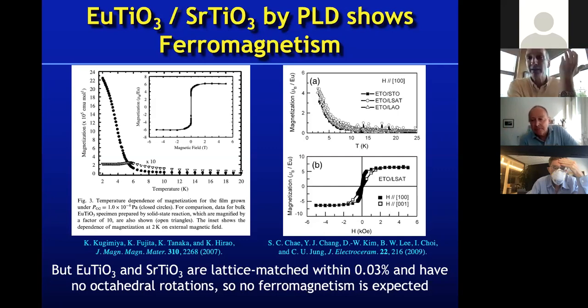When you're growing this by PLD, the natural thing to do is to grow at low pressure. Now PLD involves energetic species. When the laser interacts with the target, the ablated species come off with tens or even 100 electron volts of energy. If you're doing PLD under common conditions, which are higher pressures, maybe 100 millitorr, those species undergo a lot of collisions on the way from the target to the film. And when they get to the film, they can have much lower energies and not give rise to bombardment effects.